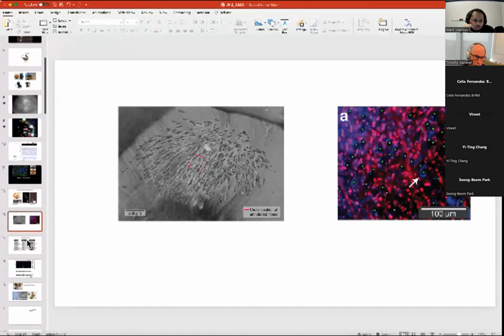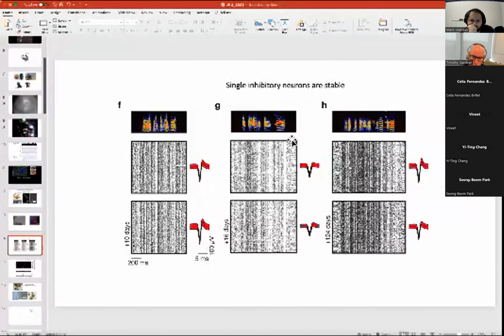And what that allowed us to do is basically get the very first chronic signals from inhibitory neurons, so stable recordings from these dense firing cells. And these are very small neurons in the song system, typically ranging from 8 to 12 microns in diameter, challenging to record single units. So we were really excited by the yield from these carbon fiber electrodes and stability in this outlier case of 124 days. And that put a counterpoint to the excitatory neurons that we had recorded previously.